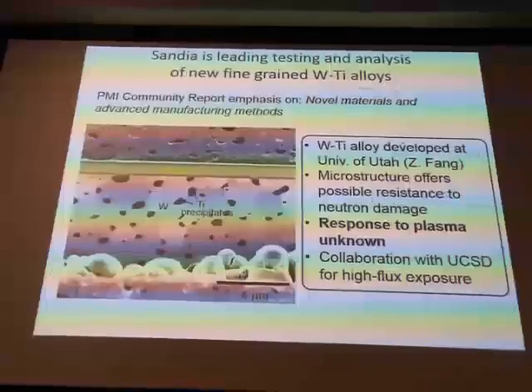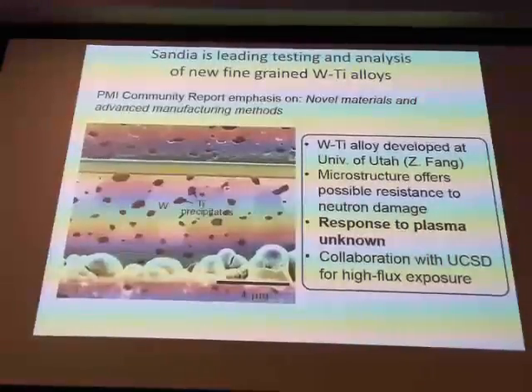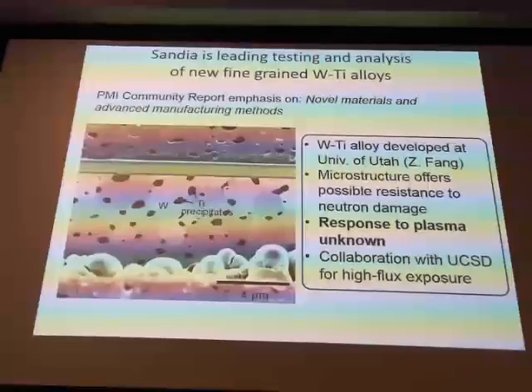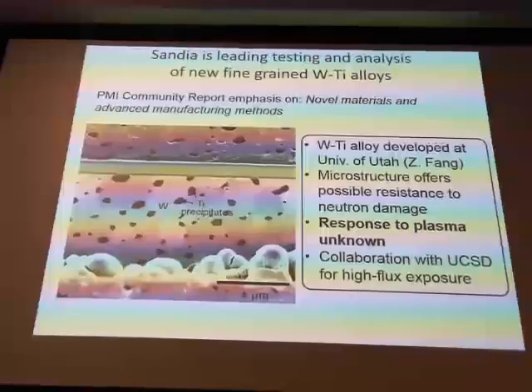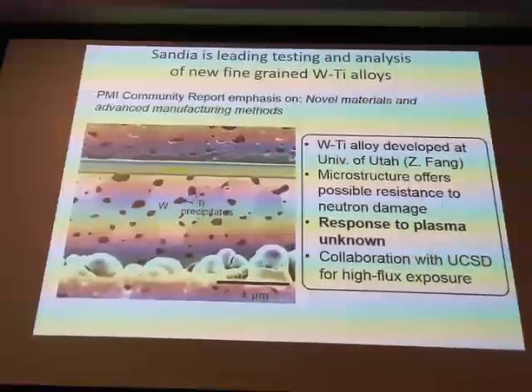So, the other issue associated with these near-surface structures is that, if you have a transient high heat load on these structures, they're not very well thermally connected to the surface, and it could vaporize them as a result. And so, it's worth considering different materials that might offer better mechanical properties or mechanical resistance to that. And so we looked at some ultra-fine grained tungsten materials, and that's what's shown here. This is a cross-section. These small, darker grains are titanium. It'd be more appropriate to call them titanium dispersoids, but essentially these pin the grains down to prevent larger growth. And so in this case, the grain size is restricted to about 960 nanometers or so.